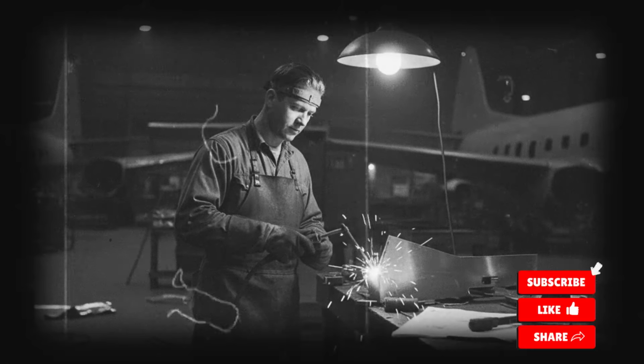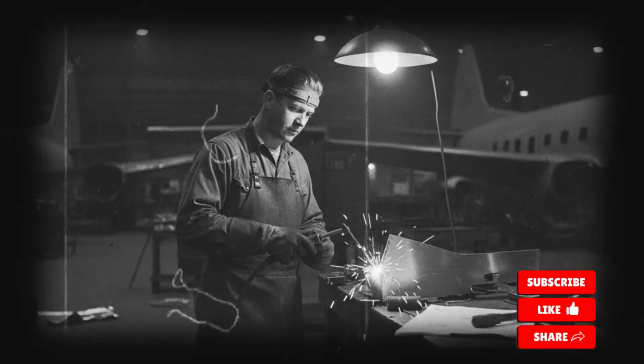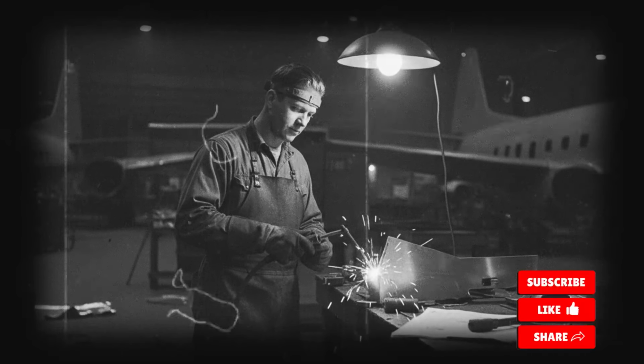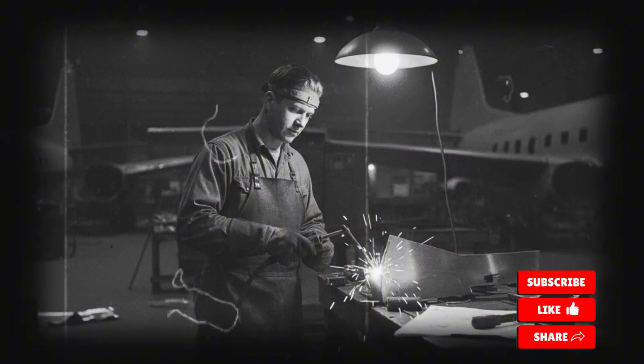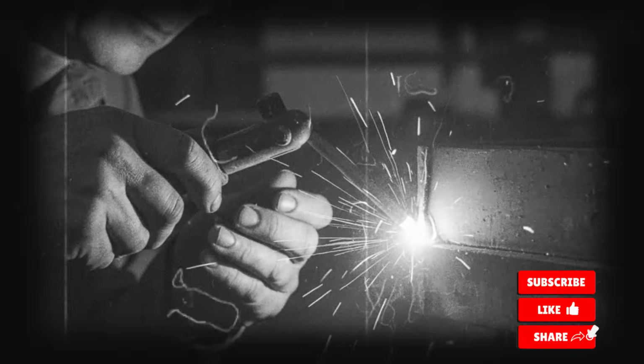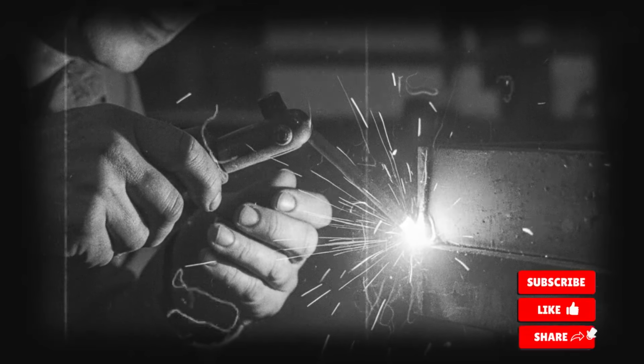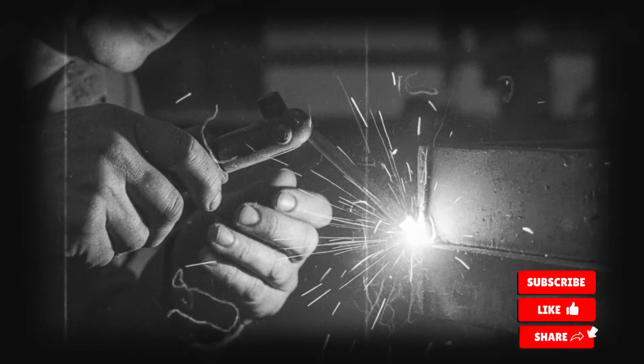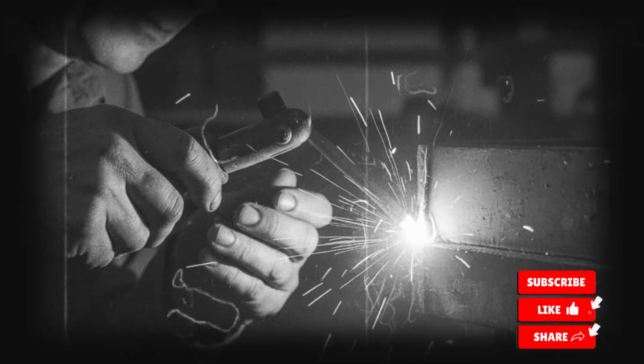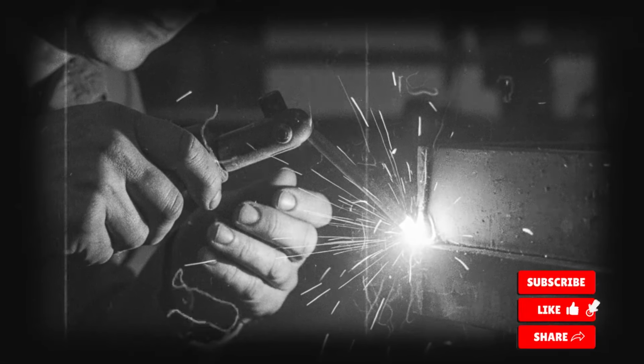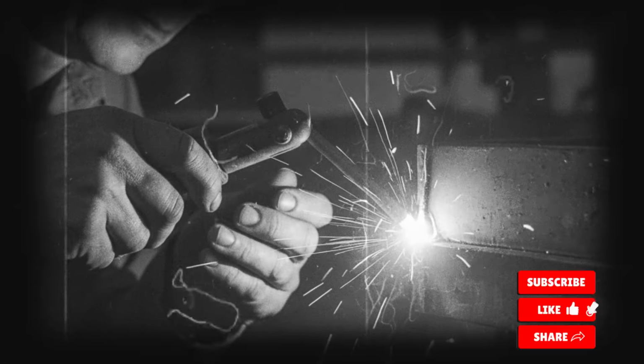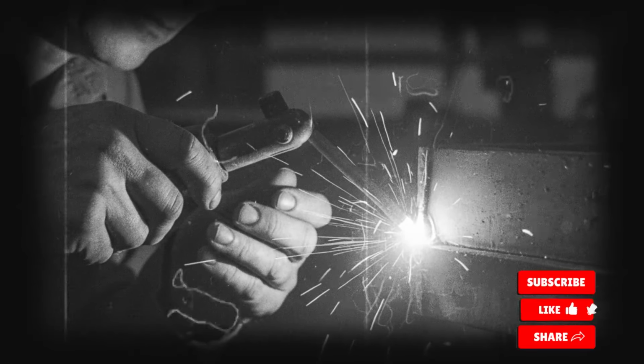The aircraft performed perfectly. Pressurization held at 40,000 feet. Structures withstood maneuvering loads. After 20 hours of punishing flight testing, inspectors found no evidence of distress in welded areas. On July 19, 1944, General Myers rescinded the grounding order. The B-29s with Henderson's welded joints were cleared to return to combat operations.